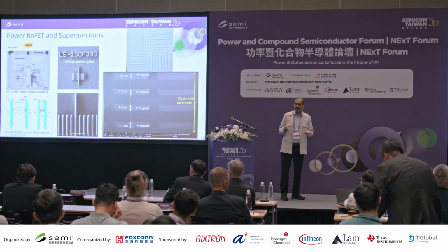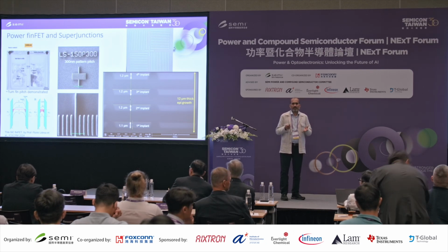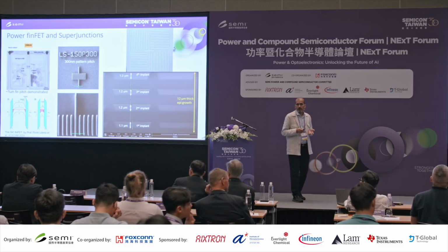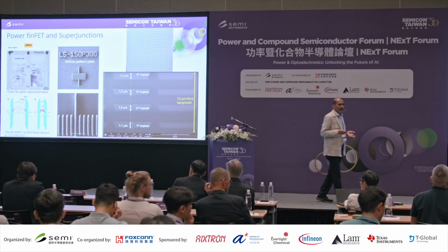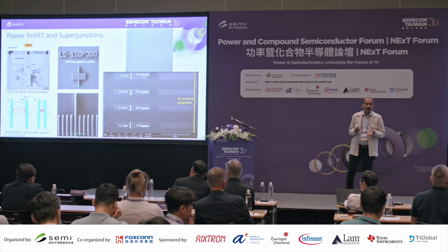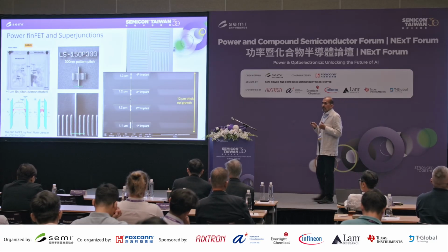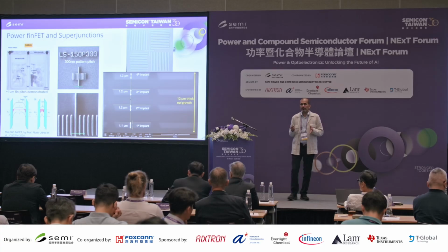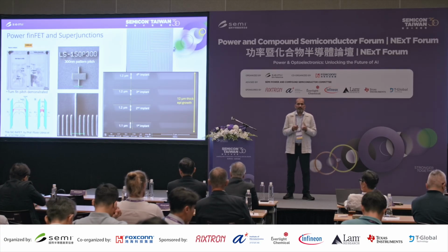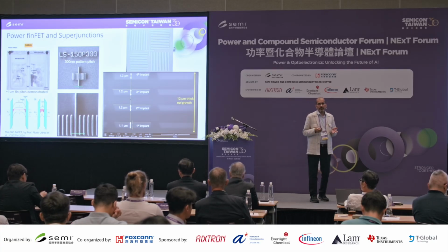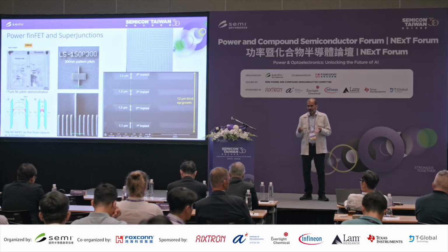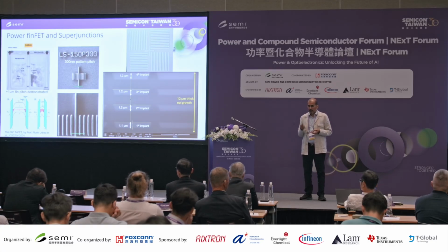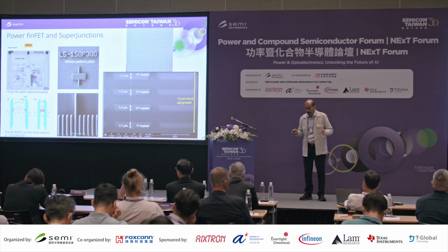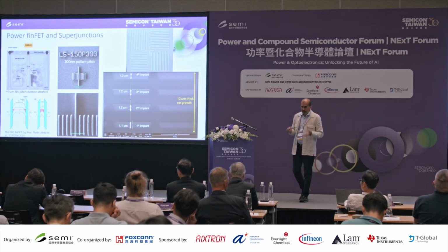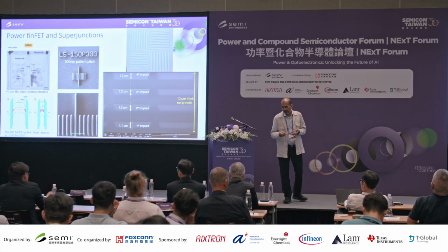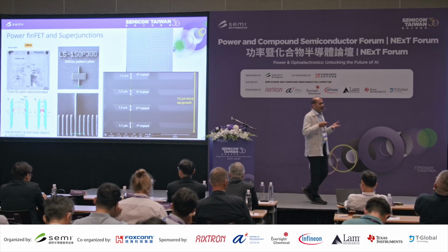We have a scanner which can resolve down to 110 nanometer on transparent silicon carbide wafer. That means we can have a fin density of 110 and 110, which is 220. We have demonstrated here 300 nanometer, which is 150 and 150. That means our lithography is fully ready for fin type devices, and on the right bottom is the implant scheme.